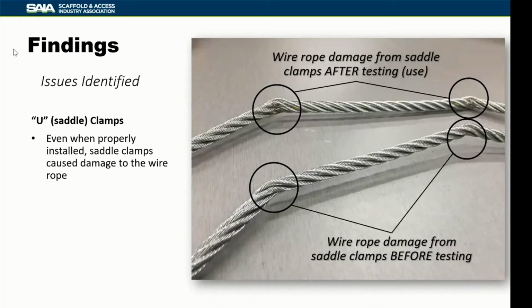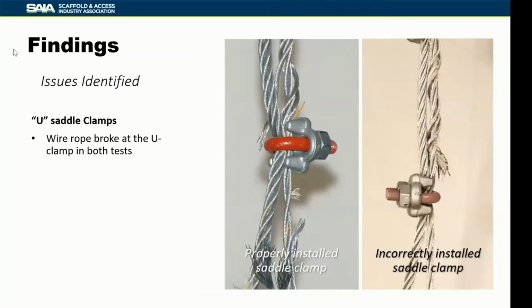simply by installing those clamps. And then when you compound that with the poor performance of the U-clamps when you install them incorrectly, which can very easily be done, you can understand why in our industry U-clamps are not permitted to be used. And you can see here again, because of the damage done to the wire rope, we do actually fail the wire rope right under the U-clamp, and we really have to attribute that to the fact that we are damaging that wire rope before we do anything. Just simply by installing those U-clamps, you've done damage.